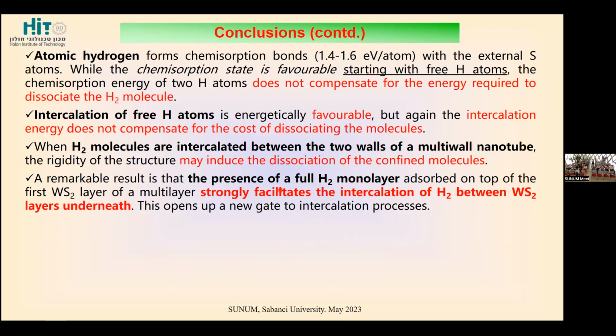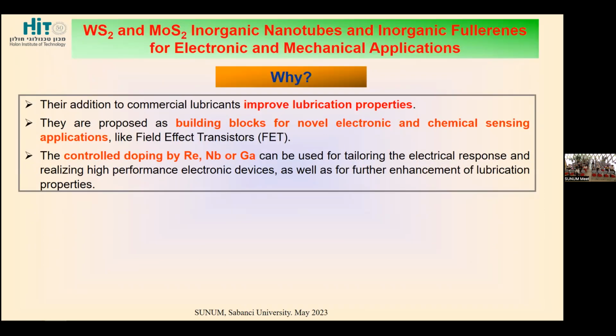Then, based on this increase of the interlayer distance by initial hydrogenation, we used this property for a different type of study, which was also initiated here in Sunum. This study was related to the fact that WS2 and MoS2 nanotubes can be used as commercial lubricants and also in various electronic devices. And this could be done by controlled doping of rhenium, niobium, or gallium, so they can improve the electrical response and the electronic properties.